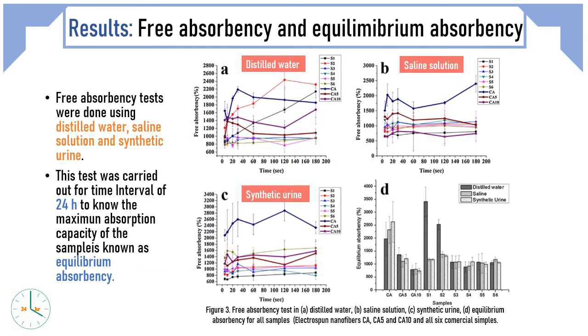This test was done to quantify the absorption capacity of sample with respect to time. As shown in the chart, it's clear that in saline solution and synthetic urine, the absorption capacity of electrospun CA nanofiber was significantly higher than any of the commercial products. In case of distilled water, CA nanofibers showed large absorption capacity as compared to all samples, except two commercial samples, S1 and S2, which were primarily based on only superabsorbent polymer.